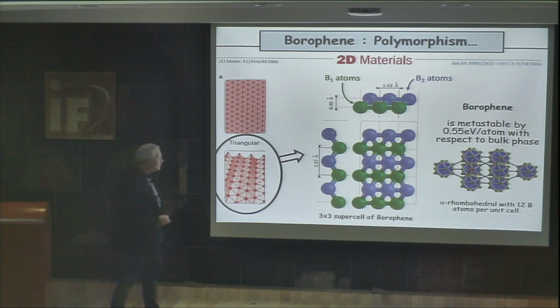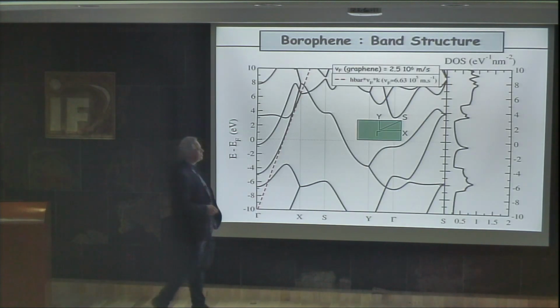So it's a little bit complicated. Boron is really a very funny material to investigate. You have clusters of boron which are connected to each other to form a 3D system. So it's quite interesting. This is the more stable 3D phase. And for example, the triangular phase is about 0.55 eV per atom less stable compared to this bulk material. But we have investigated this 2D system, and especially its electronic properties.